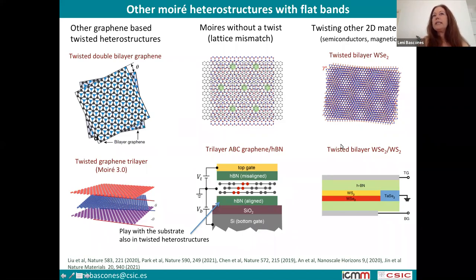So in all these systems, people have already observed correlated states. This has really opened a field which is very, very large and which is changing constantly. You can even combine things, like playing with the substrate in the twist situations. In this one, people have also observed superconductivity. In some others, there were hints of superconductivity. They have even published it, but it's not clear whether this is superconductivity. Most people believe that, for example, these two systems, this trilayer aligned with the boron nitride that I will talk about later, or these twisted double bilayer graphene, were claimed to be superconducting, but now people don't believe it's that.